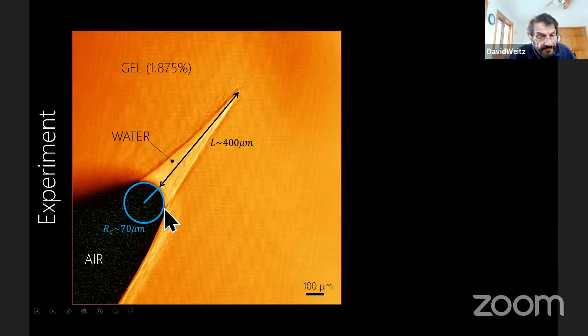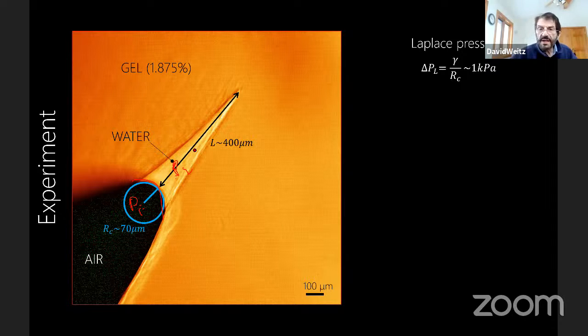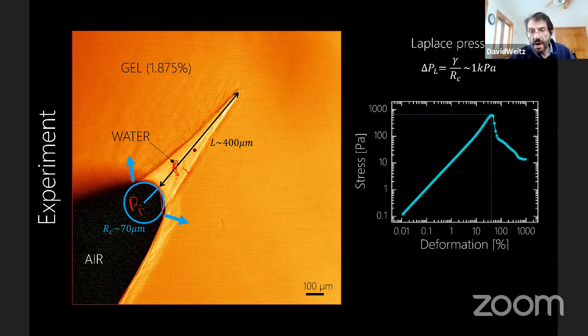Another thing we can do is fit this to a sphere, and that tells us we know the radius of curvature of a sphere. That tells us the difference in pressure. It's the Laplace pressure, the difference in pressure here and here. This is P1. This is P2. There has to be a pressure difference because of that radius of curvature. And you can calculate what it is, and it's of the order of hundreds of pascals to a kilopascal, depending on the details, what the fluids are, what the surface tensions are, what the radius is.